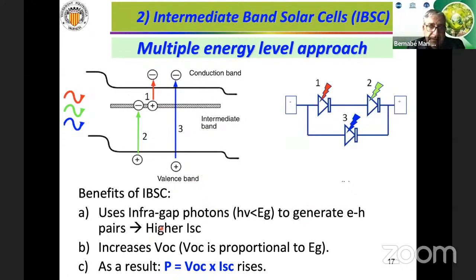And the result is we can have a higher short circuit current, and also a higher open circuit potential, because the open circuit potential VOC is proportional to the band gap. So as a result, we were able to increase the current and the open circuit voltage, so the power of our system can increase.